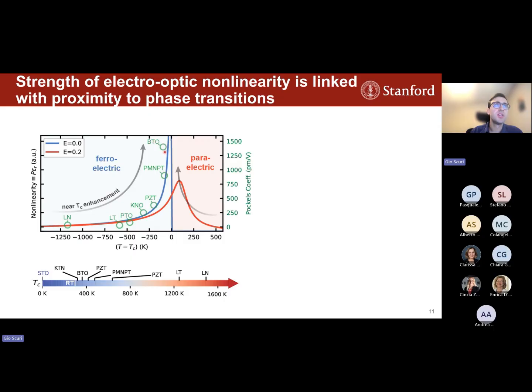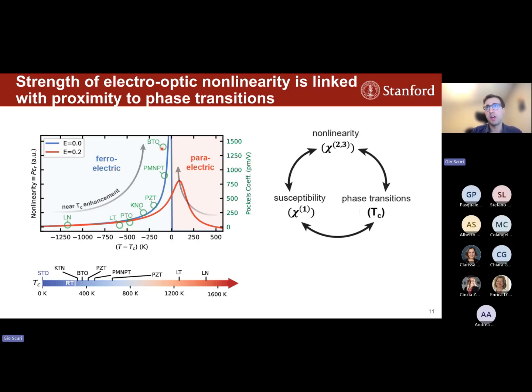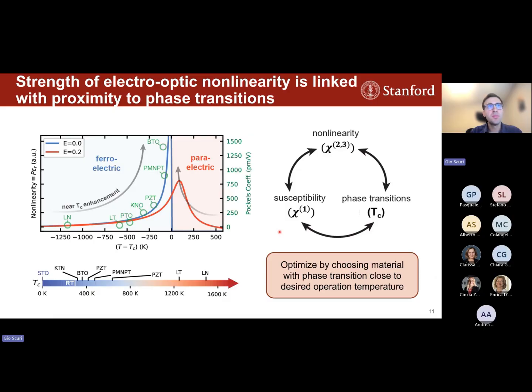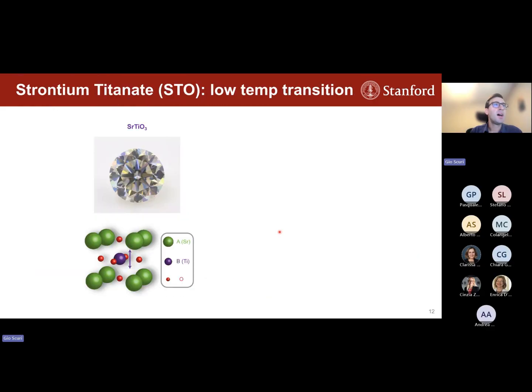And indeed, if you plot these leading materials at room temperature and their proximity to where they go from a paraelectric to ferroelectric state, you see that the most tunable ones are the ones closest to a phase transition at room temperature. And there is this very nice relationship between these electro-optic nonlinearities, phase transition, and also linear susceptibilities of the system. As a result, if you want to optimize the material specifically for an operating temperature, what you want to really do is choose a material that has a phase transition close to that operating temperature. And it turns out that there was a material that has this low temperature transition. It's known as strontium titanate.